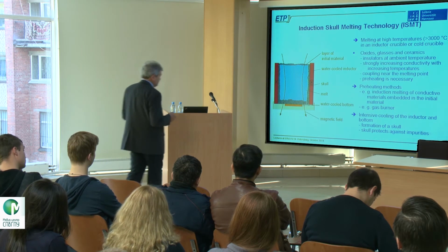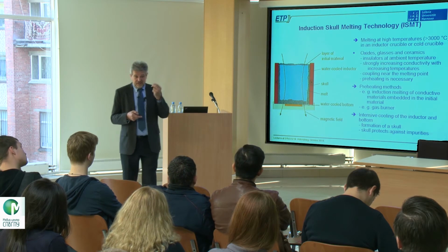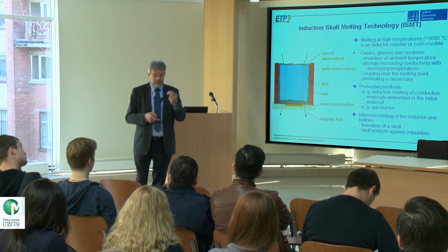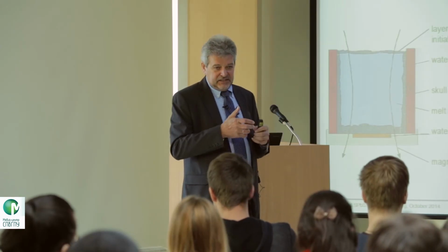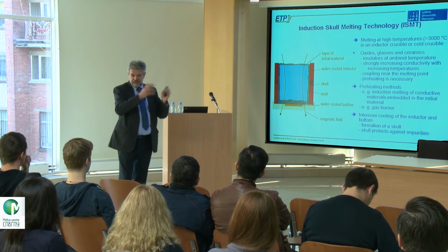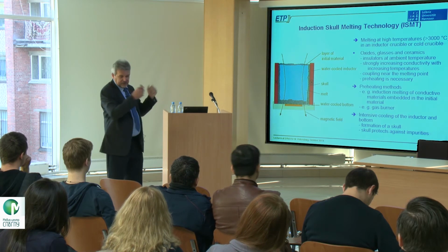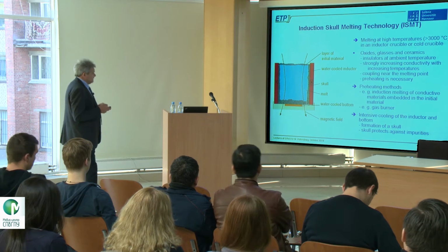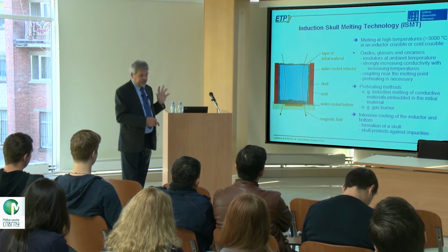But in the case of oxides, the temperatures are too high for gas burners. We use the metal of the oxide. If you want to melt aluminum oxide, you use some pieces of aluminum. You put these aluminum pieces inside the powder. The aluminum is coupling. It is overheating. Heat cannot go away. And then it is heating the powder around. And so it generates a small area of high temperature, and then it's coupling, and then it is starting. This is a typical starting process.